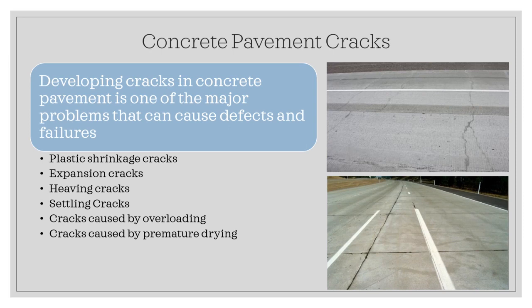And settling of that may be a result of poor soil compaction underneath the slab. Settling cracks typically occur in a situation where a void is created in the ground below the concrete surface. This is another reason. The other type of crack is caused by overloading on the slab. This is very common and sometimes can be combined with other types of cracks mentioned earlier. And finally, the crack caused by premature drying.